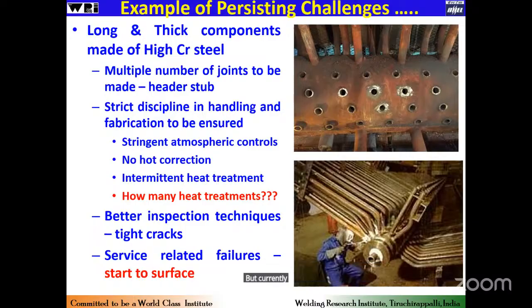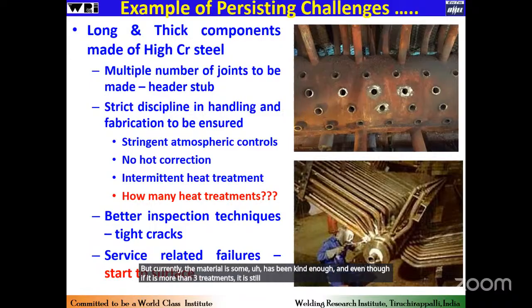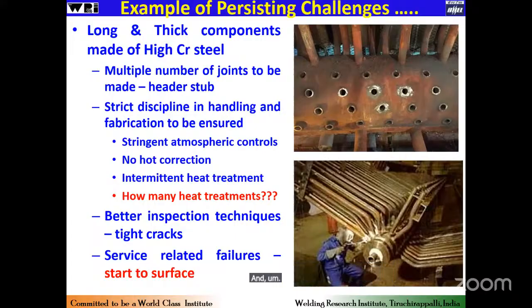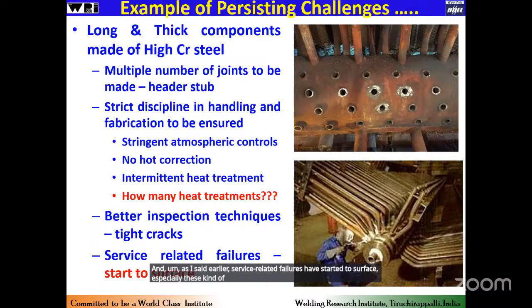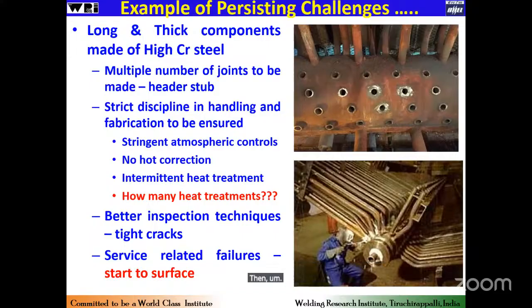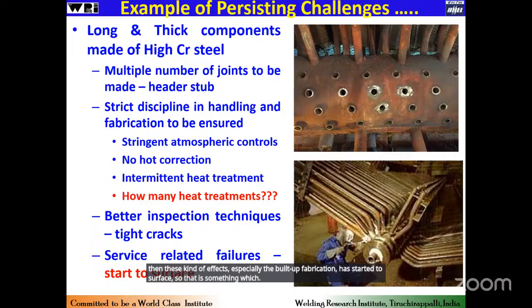But currently the material has been kind enough, and even if it is more than 3 treatments, it is still tolerating and working fine. And we may have to go for better inspection techniques, especially with respect to tight cracks. And as I said earlier, service related failures have started to surface. These kinds of materials are highly prone to a typical problem called type 4 cracking, which occurs only in service. So when we push the material to the service condition it is actually meant for, then these kinds of defects, especially in the welded fabrication, have started to surface. So that is something which we have to see how we are going to address.